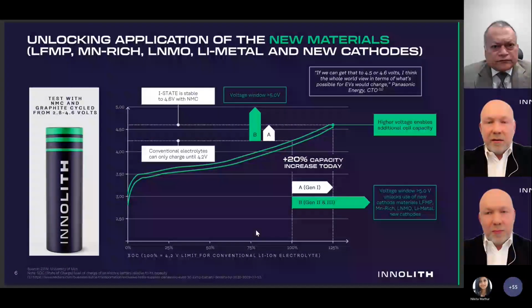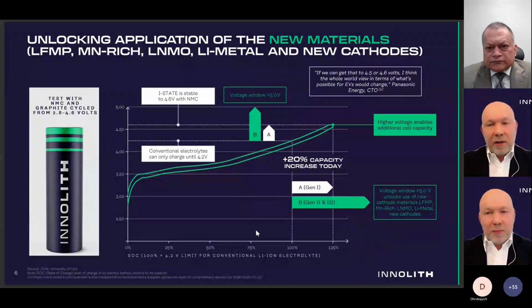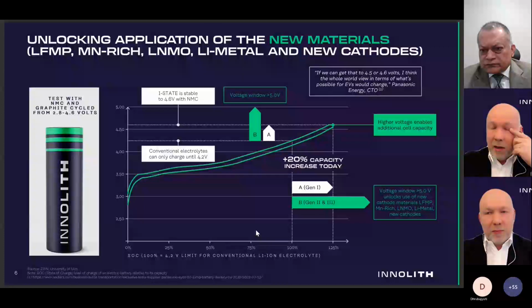Our electrolyte has a special high stability to voltages of up to 5 volts. For those of you who are familiar with electrochemistry, maybe it's not a very informative slide. For others, just to explain in a few words how inorganic electrolyte works: the conventional one usually is cycled up to 4.2 volts, and that is the limitation. Beyond this voltage, the electrolyte becomes unstable. With 4.2 volts in the cell, a conventional or existing battery manufacturer would get 100% of the capacity accessible for them with the set cathode and anode material. Our electrolyte is stable to higher voltages, as I've mentioned, up to 5 volts.